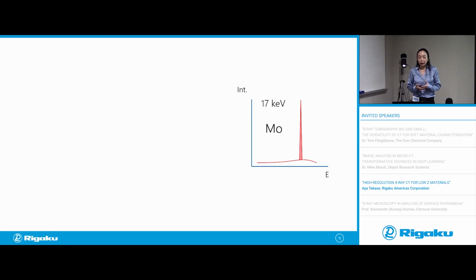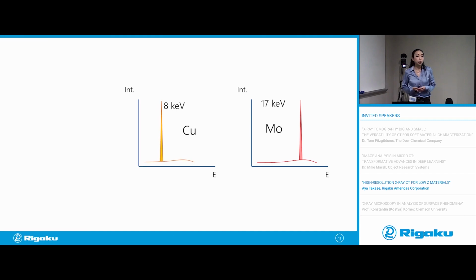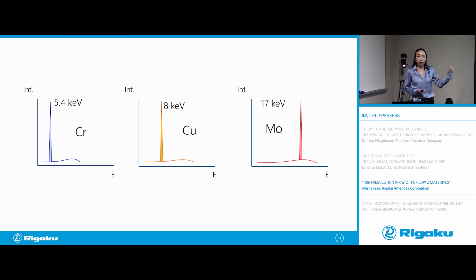If 17 is not low enough, you can use copper because copper's characteristic radiation is at 8 keV. If you need something even lower than that, then you can use chromium. Chromium would give you 5.4 keV energy radiation. Those are three typical target materials you can use if you need really low energy X-rays, but you don't want to lose a whole lot of X-ray intensity. Now, how much of a difference does it make, depending on the energy of X-rays you use, in terms of contrast?